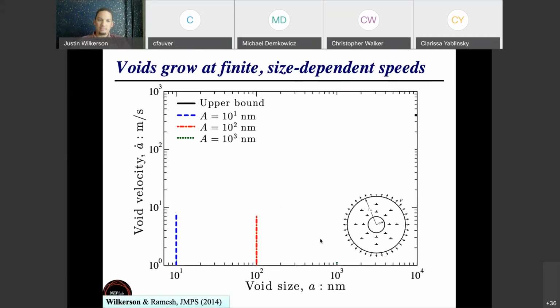the kinetics of voids. So here I'm going to show three different voids of three different initial sizes, 10 nanometers, 100 nanometers, and 1 micron, and then show how their velocity evolves as the void grows. Okay, so the x-axis here is showing you the current void size as the void grows with time, and then the y-axis is the velocity at which it's growing.